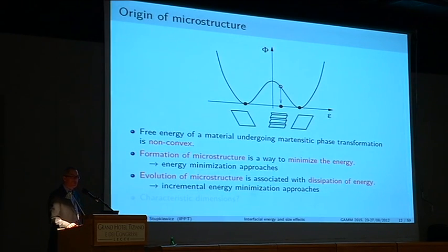So what is the origin of the microstructure? The origin is typically associated with the fact that the free energy of a material undergoing phase transformation is non-convex. Therefore, if you see such a sketch of a two-well free energy with two minima at some specific strains, if you are somewhere in between, the way to minimize energy is to mix the two variants, the two phases, and then in this way you can lower the energy.